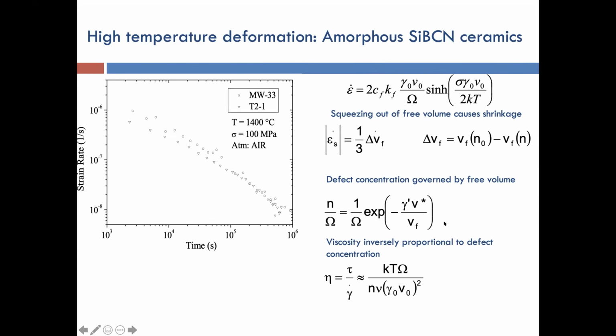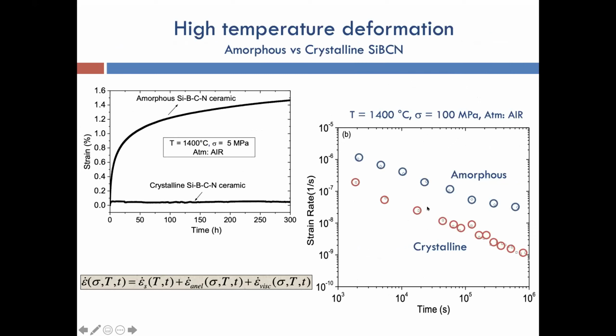I'll not go into the mathematics part of it, but I would like to summarize our deformation behavior in these materials in this one single plot, which gives you an idea of the kind of strain rates we talk of, in the order of around 10 power minus 9, which is extremely important. For example, if you take a jet engine produced by GE, we are talking about strains in the order of around 0.1%. So if you can make sure that your samples do not deform beyond 0.1%, then the material is stable.